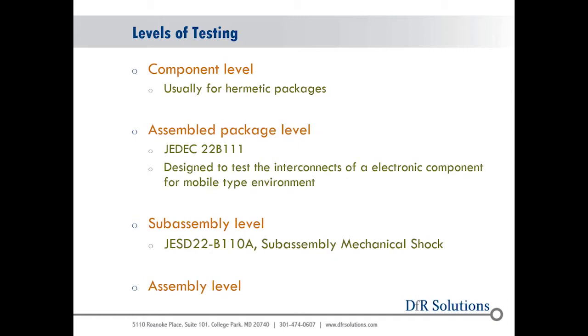So then we have assembled package level testing. This is really component package qualification type of testing. This is coupon level testing, where I solder a new package onto a test coupon. I subject it to a very high shock level, typically 1500 Gs, half milliseconds, really for cell phone types of environments. And then we get to subassembly and assembly level types of drop testing.